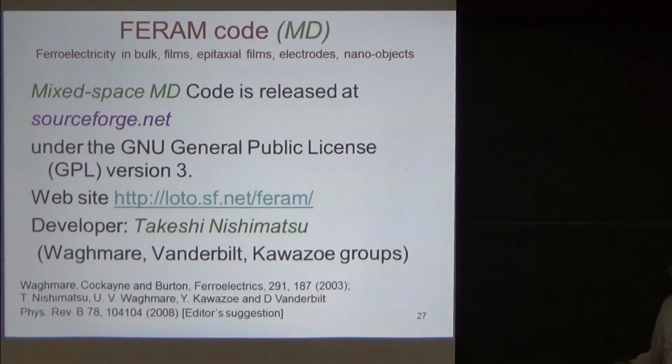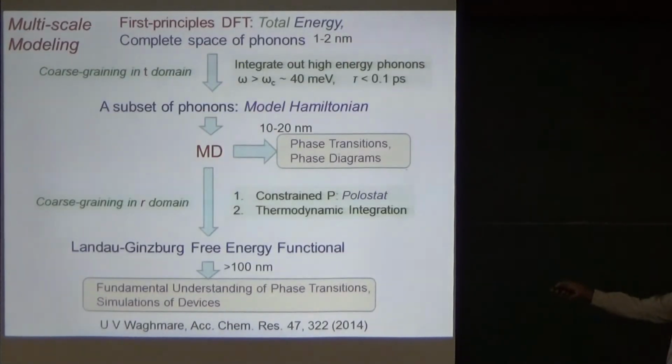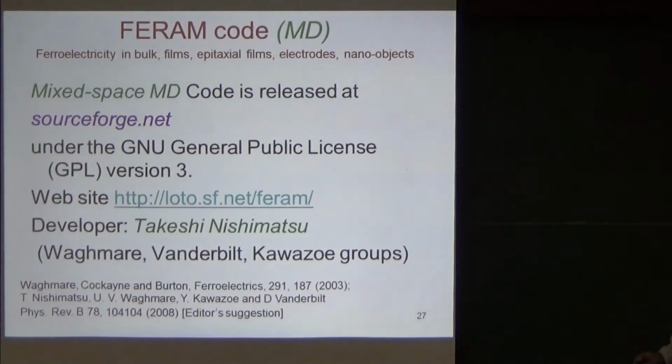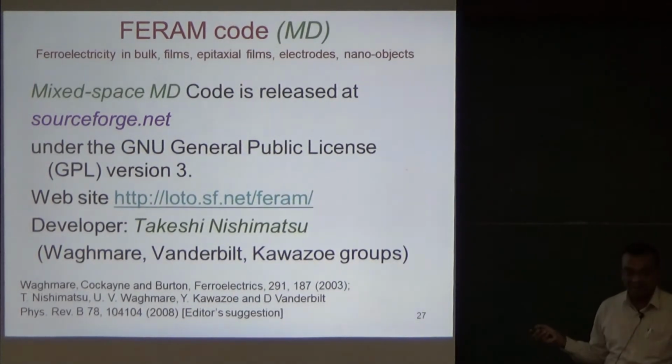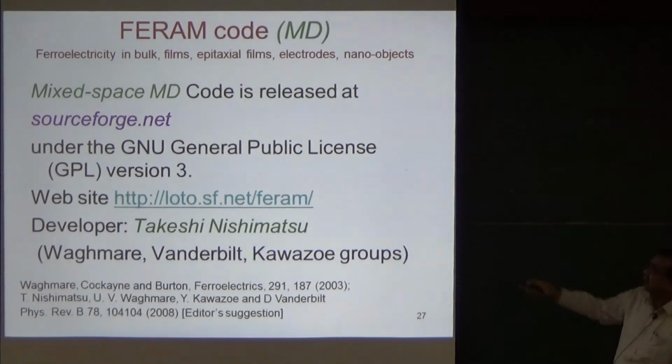For the first part, molecular dynamics, we have our own open source software called the FERAM code, developed by my ex-postdoc Takeshi Nishimatsu. This code is very useful for doing MD for large scale simulations of ferroelectric oxides. It's called mixed space molecular dynamics, meaning the infinite range interactions are treated in reciprocal space, so it's very efficient in that.